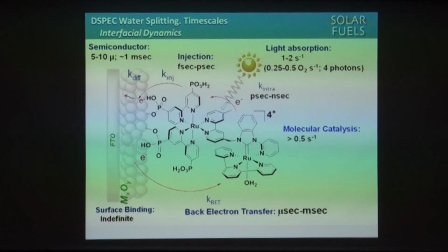Then there's a competition. The electrons have to drift through the TiO₂ to get to the underlying conducting oxide in competition with back electron transfer. I keep talking about that. Now you'll see why. In these thick films, say 10 to 15 microns in the end, it takes milliseconds for the electron to drift all the way through the oxide. It's very slow. It's a semiconductor, but still it's slow. Back electron transfer occurs on a microsecond time scale.